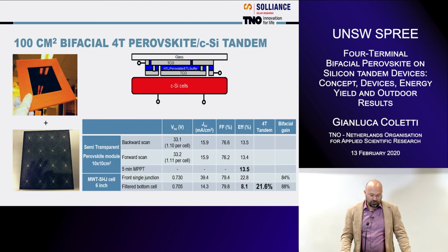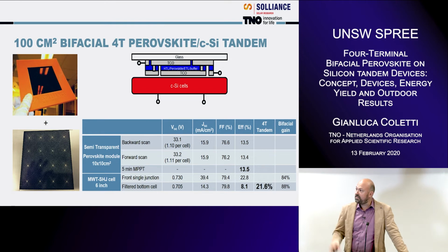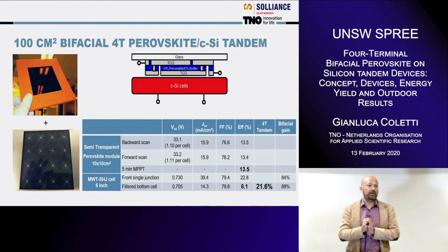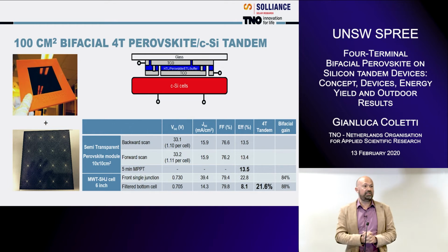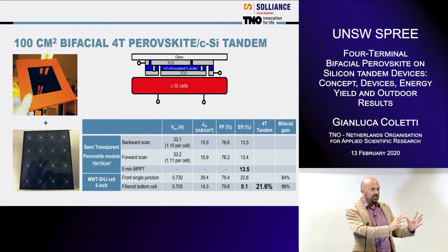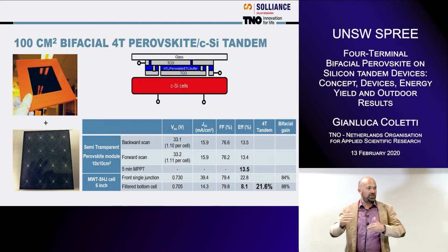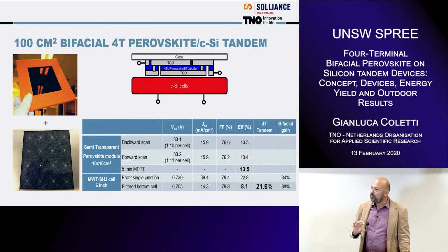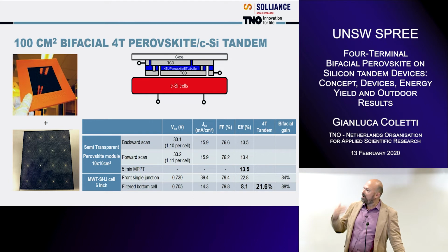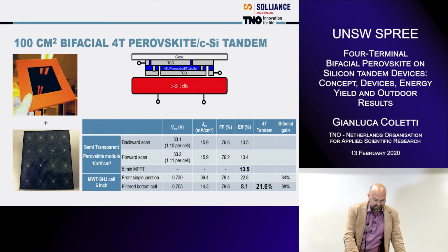So this device produces 13.5% efficiency, 5 minutes at MPPT, and we put that on top of our MWT-SHJ silicon heterojunction. We obtain 8.1% efficiency point from the bottom device. With the top device you get 21.6. As you see, we didn't achieve back the original efficiency of the single junction device, but this is a much larger area. And we didn't implement here the highly transparent layer that makes the bottom device also boost the efficiency.